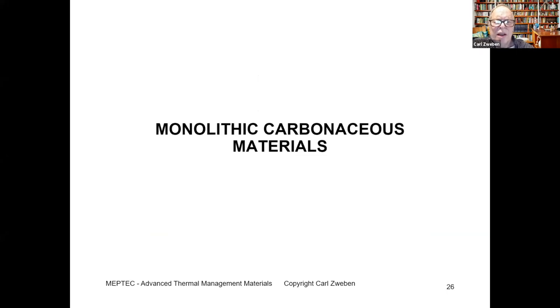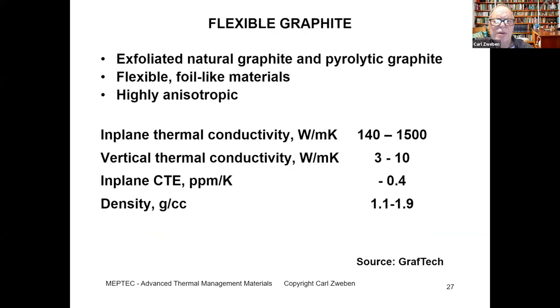So let's start looking at monolithic carbonaceous materials. We start with flexible graphite, which has two subcategories, exfoliated natural graphite and pyrolytic graphite. These are flexible foil-like materials, highly anisotropic. If we look at in-plane thermal conductivities, they range from 140 to 1500. And in the vertical or through thickness direction, they're much lower, 3 to 10.